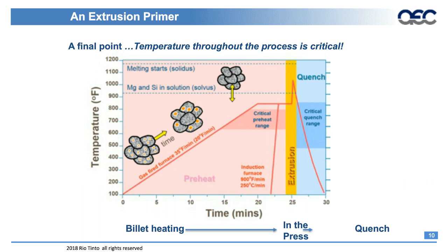So at the quench time, that could either be air if it's a relatively small, thin-walled profile, to some type of water mist, to sometimes a tank where you actually dump the extrusion into a tank of water if it's a very heavy profile that's coming out. So that's kind of the basics of what's happening during the extrusion process, and we'll come back to this a little bit more as we talk about some of the automotive applications and things like that, where this microstructure is very important to the extrusion, the performance of the extrusion.